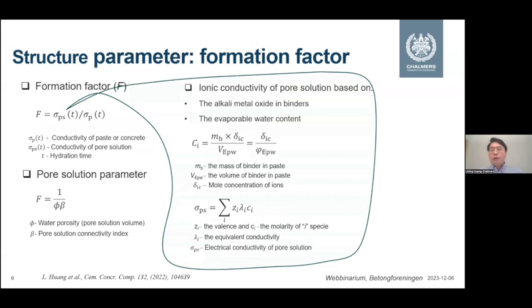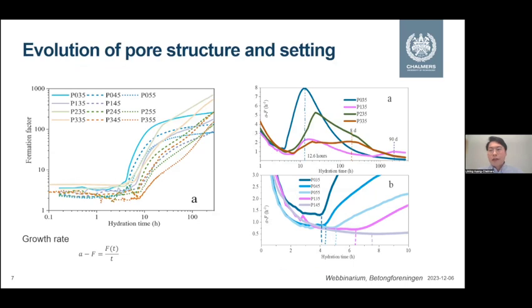The conductivity of the pore solution we can estimate from the concentration of ions in the solution, which can be predicted or calculated using the composition of the binders and the amount of evaporable water. I will not go into the details because of the time limitation, so if you are interested in the process, please read the details in our publications. We have the calculated conductivity of the pore solution and the measured conductivity of the paste, so we can calculate the formation factor evolution over time for different binders and pastes.